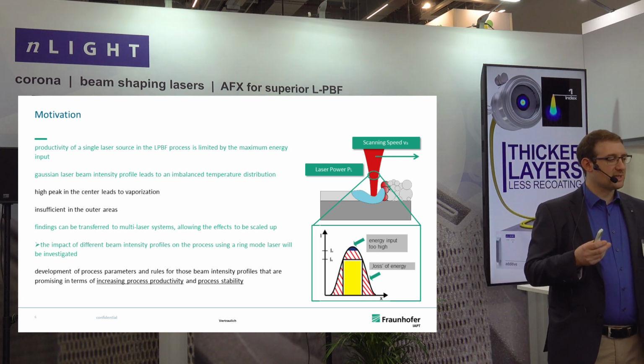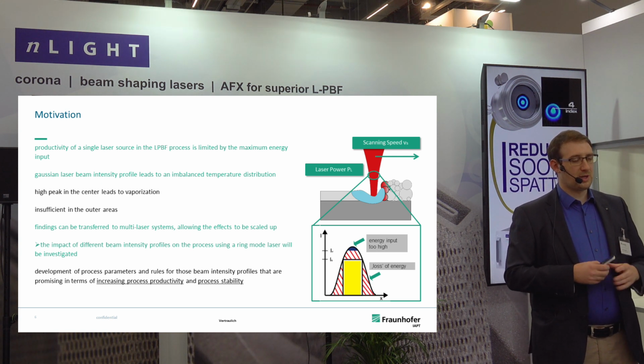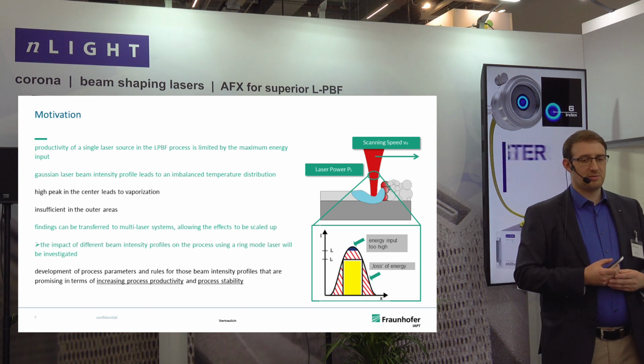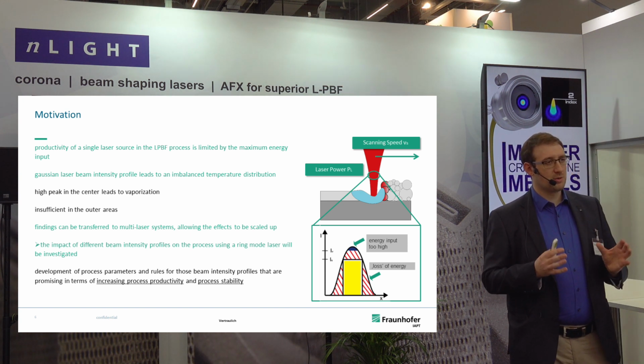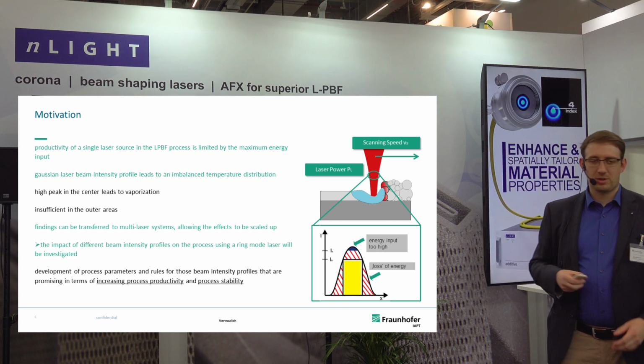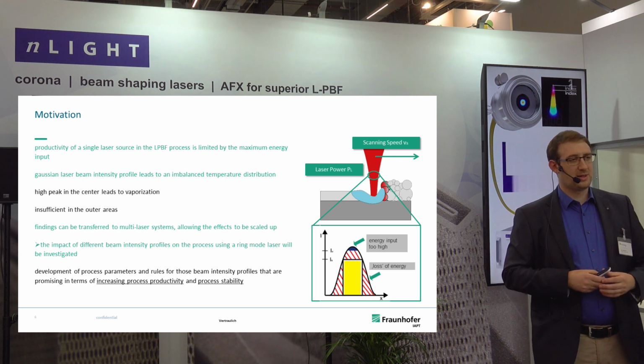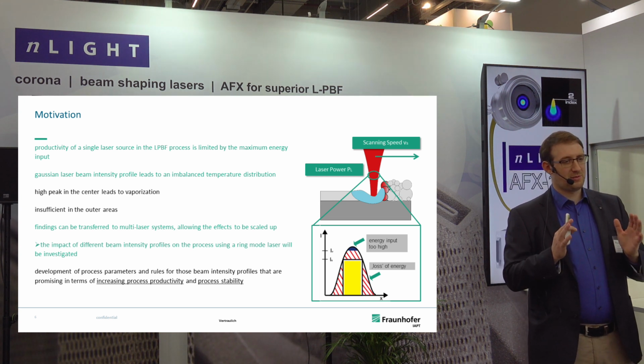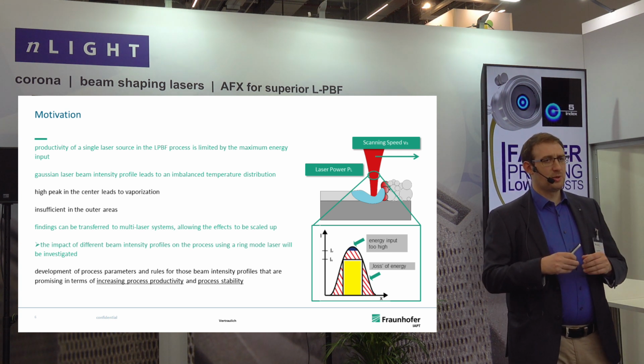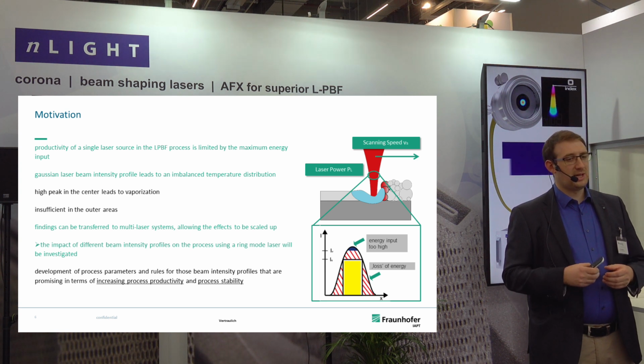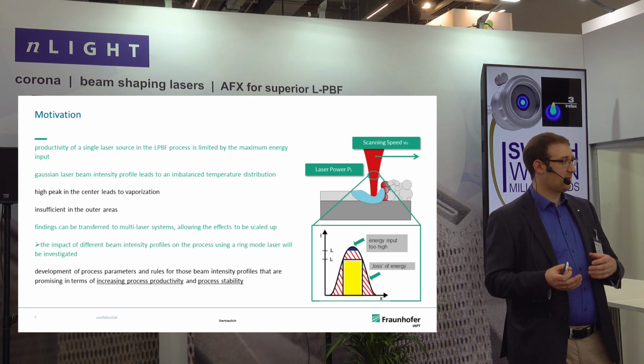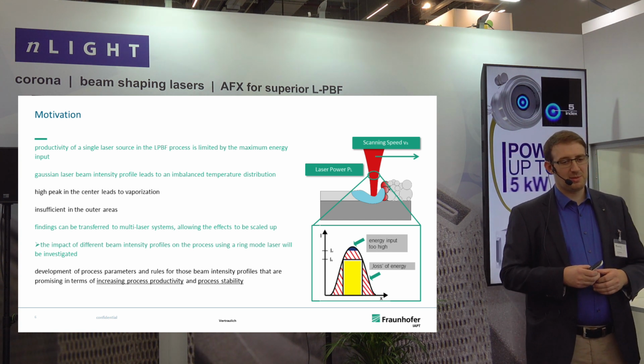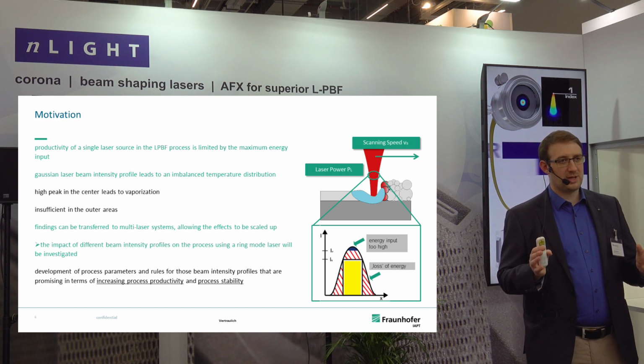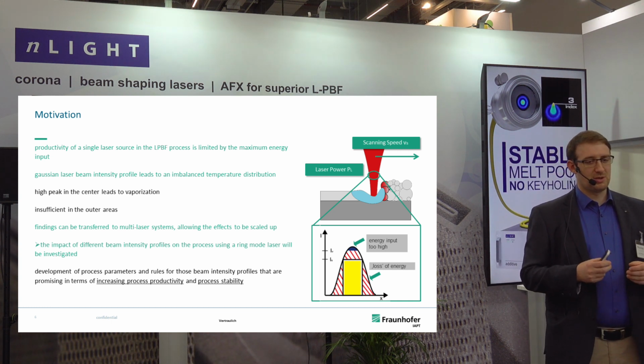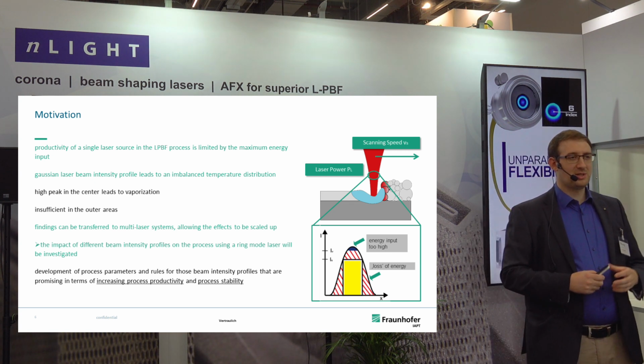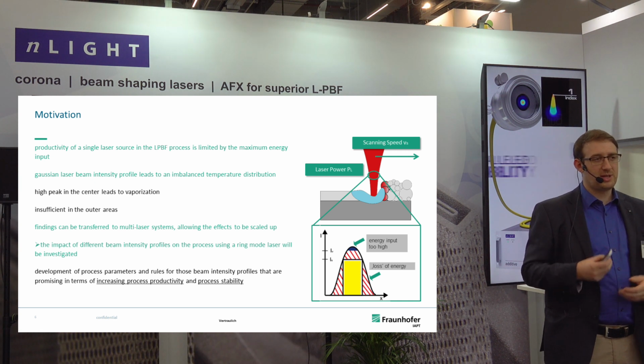But then, as the number increased, the research community found out it matters how the energy is distributed into the material. Shown at the bottom right of the graph is, if we simplify the Gaussian profile, we have in the middle a high intensity peak, which might lead to evaporation of material, so the chemistry, the alloy changes, and it's not what we want to produce. At the same time, at the edges of the Gaussian beam profile, the energy is not high enough. So, quote unquote, we lose some energy because it is not high enough to melt the material.